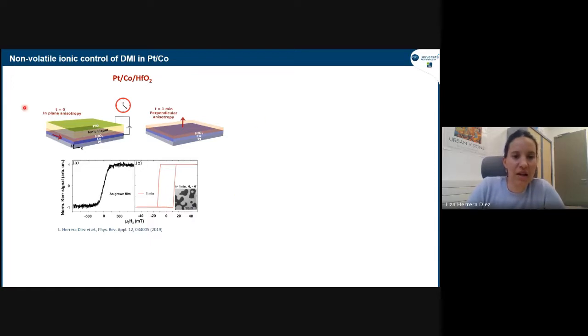So this I showed a little bit before. It's platinum cobalt. We put this hafnium oxide layer to protect it from oxidation, and also because it's an oxide that is used because of its ion mobility. So it's actually used a lot in memristors, for example. So it's an oxide that is really adapted for ionics. So we put it on top. We put the ionic liquid on top of that.